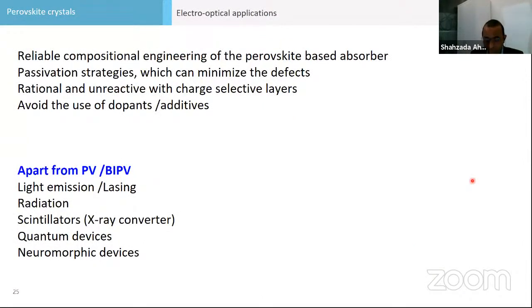To make perovskite more stable and better, we need new compositional engineering so that the stability can be increased and light absorption can be enhanced. There are stability issues and there are defects on the surface. By passivation strategy, we can minimize the defects, because grain boundaries and defects allow recombination. We also need to develop different p-type and n-type layers. I will come to that later.